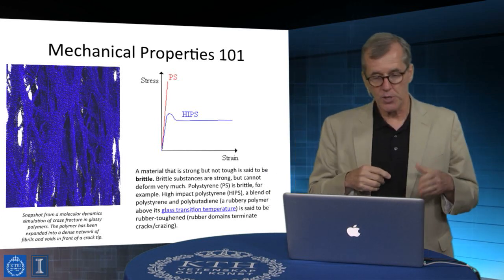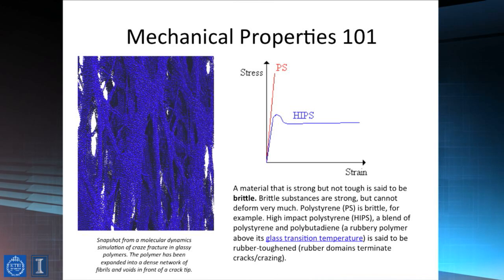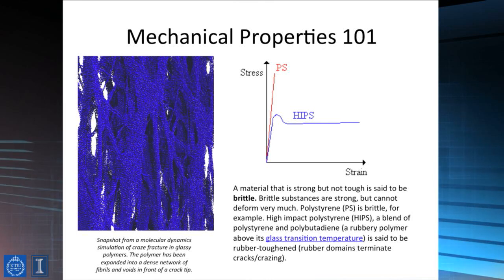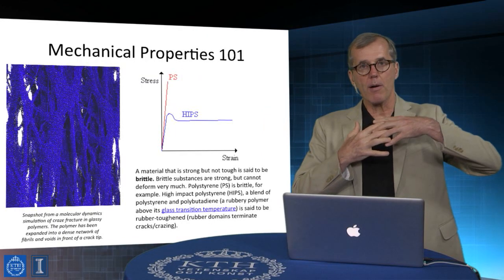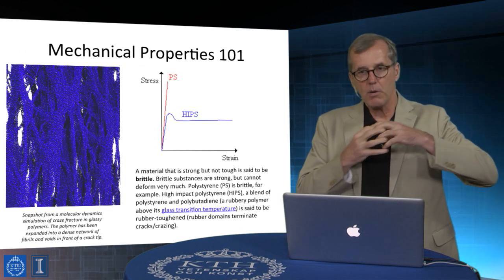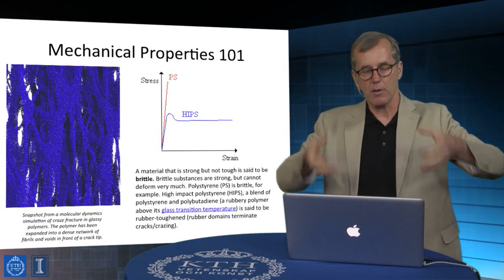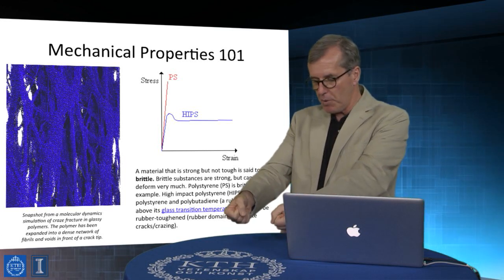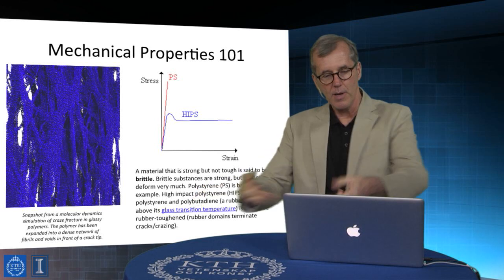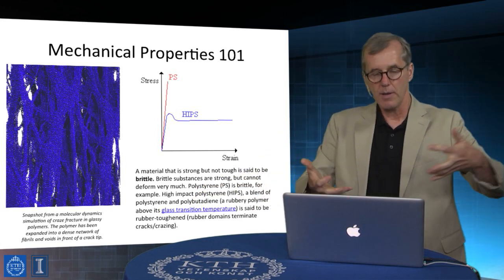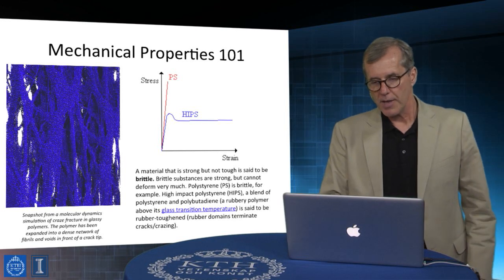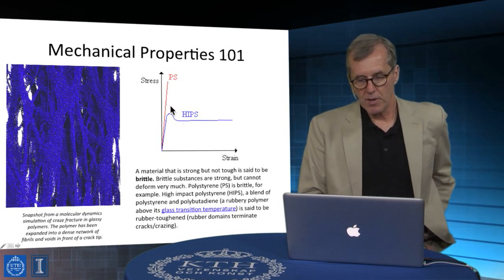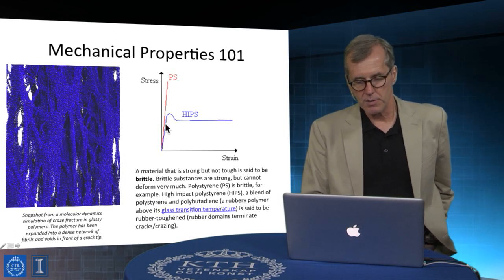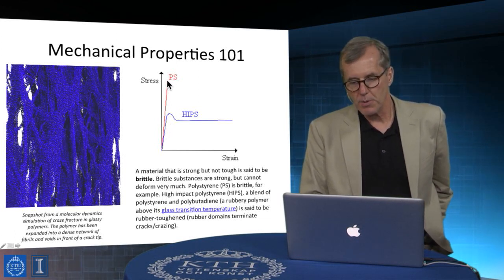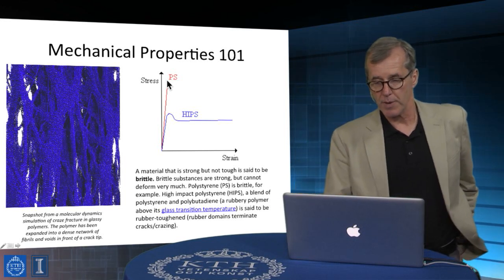And that's illustrated in the picture shown on the left, which is a computer simulation of a phenomenon called crazing. And that is, this polymer doesn't break. It actually comes apart, kind of like pulling apart a pot of spaghetti by dumping it out on a table and grabbing it on both sides and pulling it a little bit, and you find that clumps of strings come apart and void spaces form. And that's why polystyrene gets cloudy like that, because of the formation of these voids. But it makes the material not very good from a mechanical perspective.